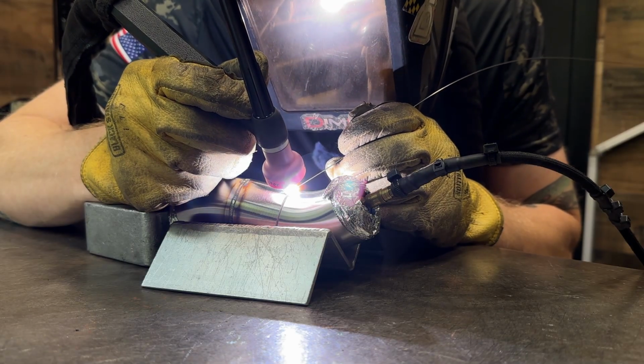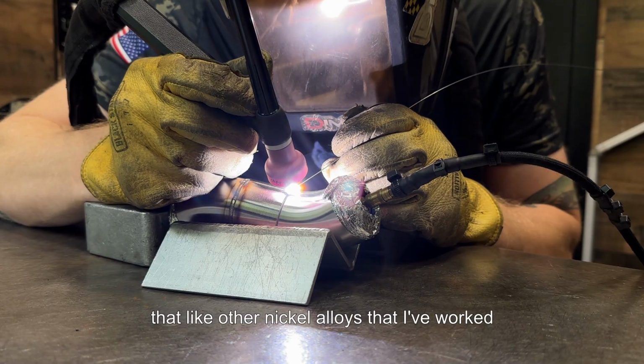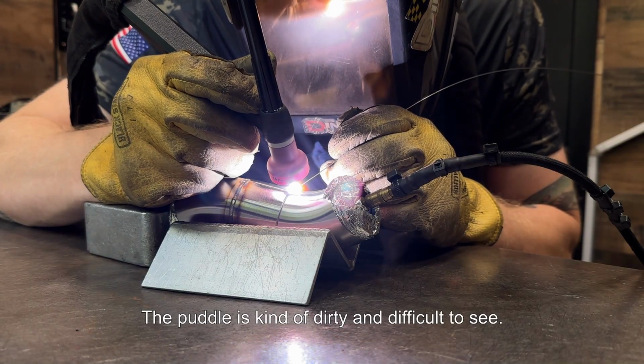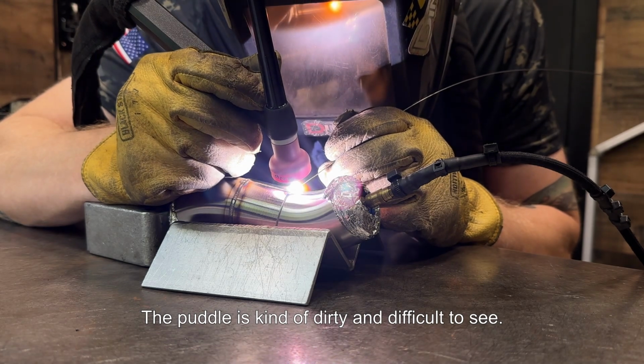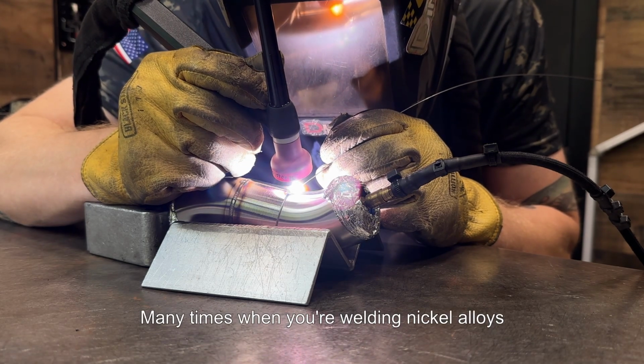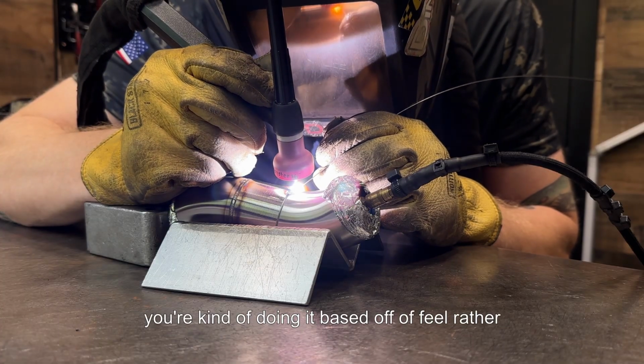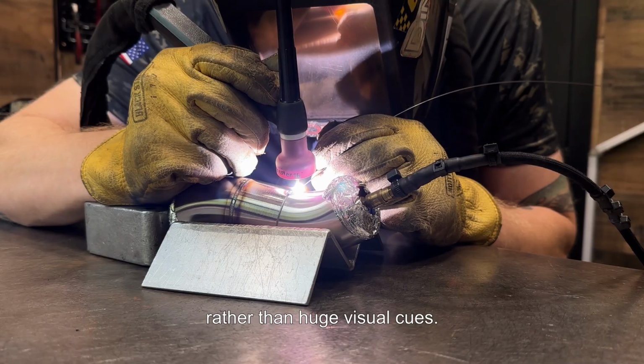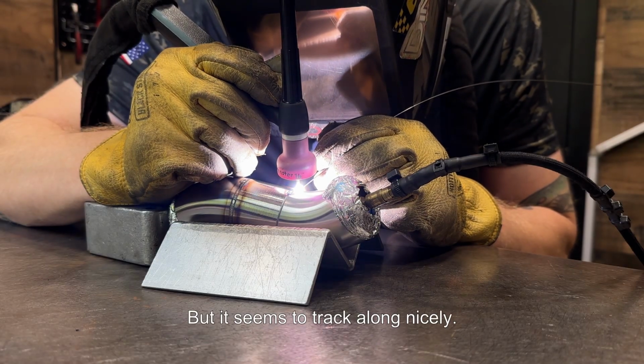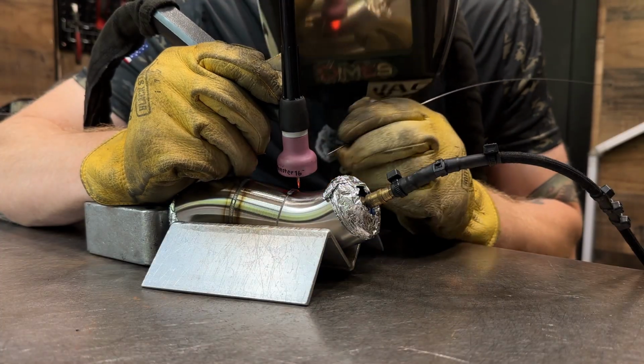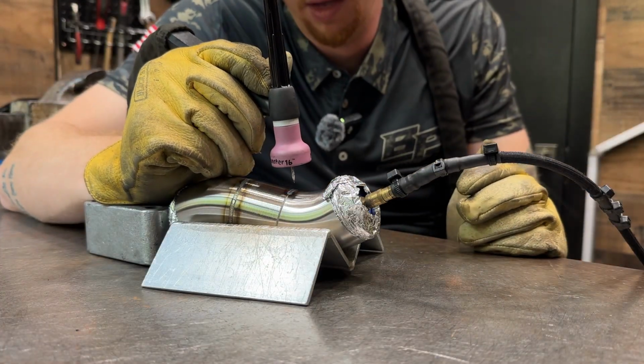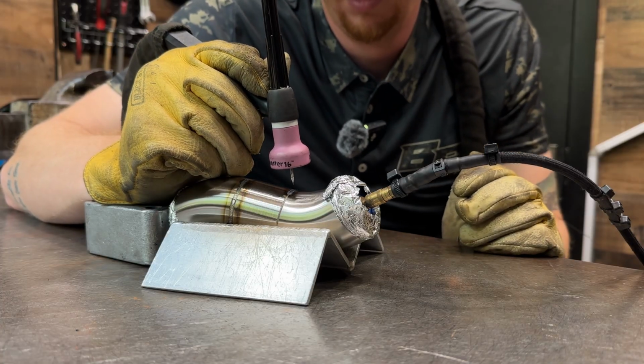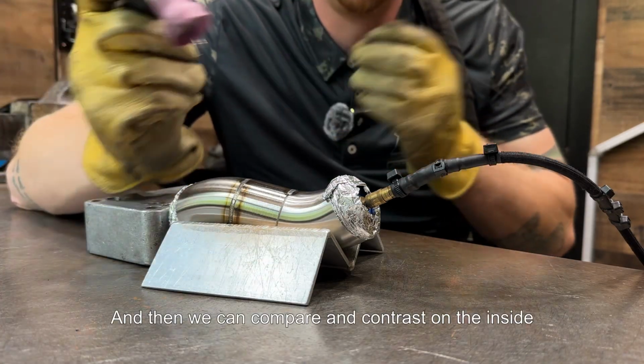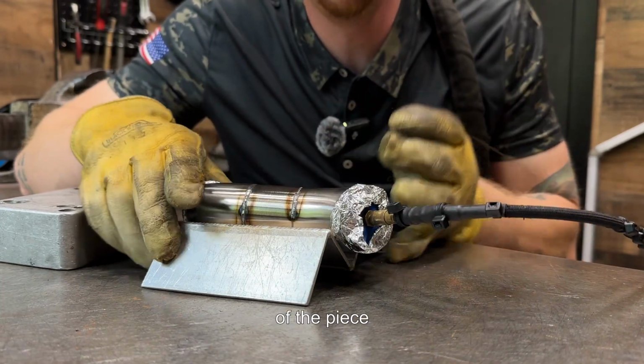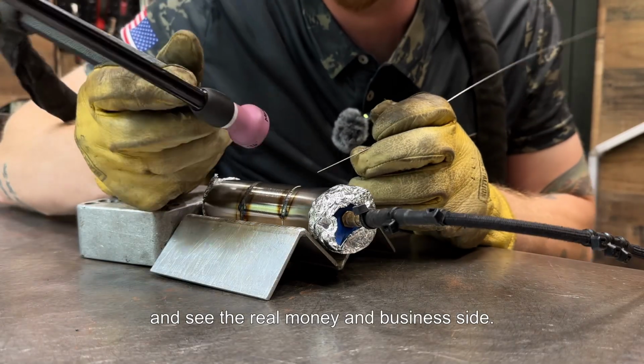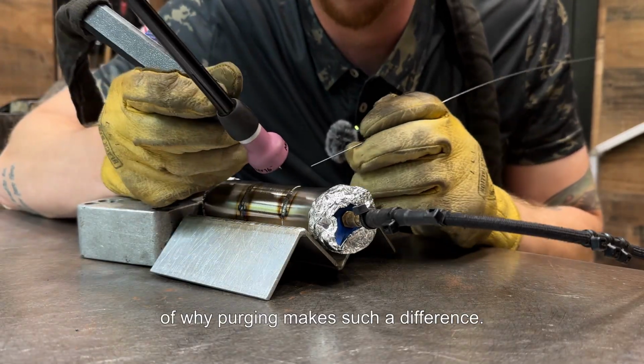So I noticed immediately that, like other nickel alloys that I've worked with in the past, the puddle is kind of dirty and difficult to see. Many times when you're welding nickel alloys, you're doing it based off of feel rather than huge visual cues. But it seems to track along nicely. The puddle's predictable, and so far so good with this weld. I'll run it the whole way around, and then we can compare and contrast on the inside of the piece and see the real money and business side of why purging makes such a difference.